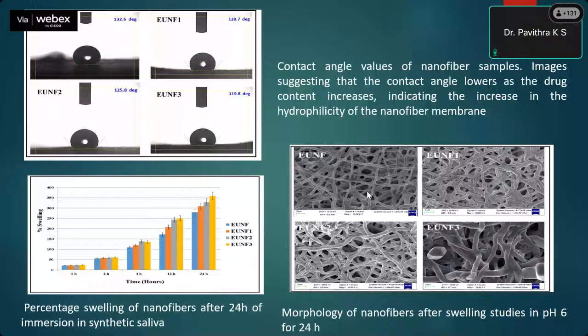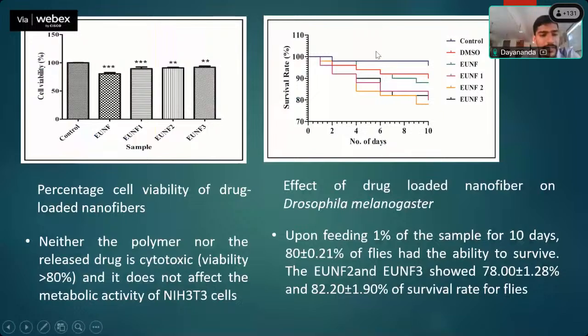Cell viability and cytotoxicity assay were also evaluated, using NIH3T3 cell line. It was found that cell viability was more than 80%, meaning almost non-toxic. Using Drosophila also, cytotoxicity was evaluated, and it was found that 80% had the ability to survive. This means the nanofiber mat and the eugenol-loaded drug compound was not toxic.